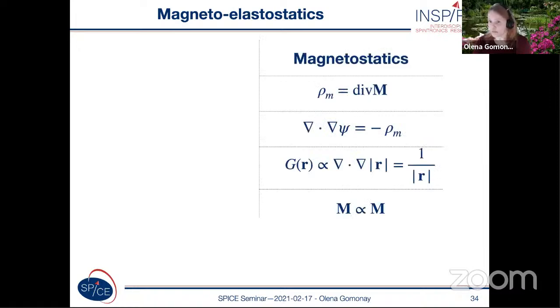If we turn to ferromagnets or ferroelectrics, we know that there the magnetic or ferroelectric order parameter creates magnetic fields, and moreover, the divergence of magnetization, so the inhomogeneity of the magnetization, is a source of additional fields, which are called magnetostatic fields or demagnetizing fields. These fields are long range, and thus they can create the domain structure which fills the whole sample, which is sensitive to distribution of magnetization as a whole sample. In antiferromagnets, the order parameter does not create any physical field. So we have a problem.